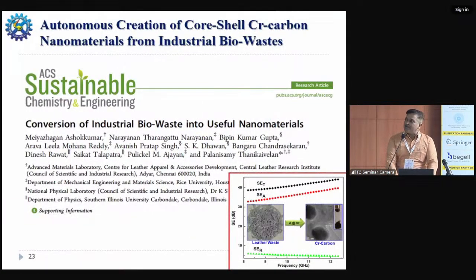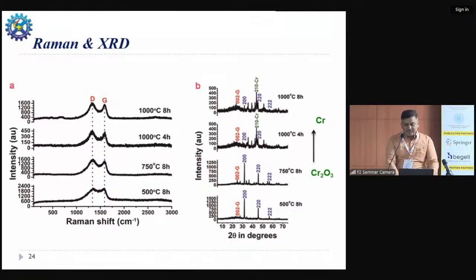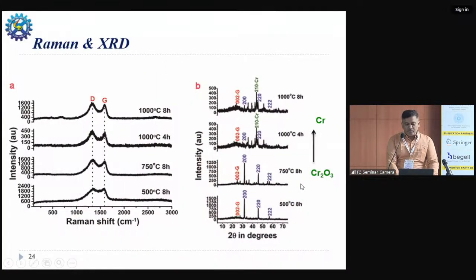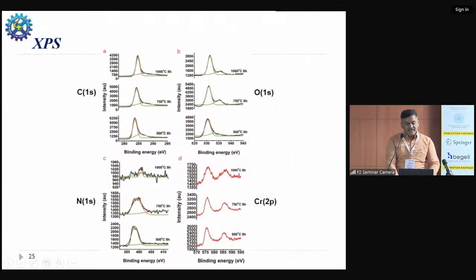And this is another example where we used chromium-containing carbon waste and subjected it to a similar kind of approach. Here we found that at high temperatures, the chromium is converted into chromium oxide at 500 to 750. But the moment you go to 1000 degrees Celsius, the chromium oxide is further converted into chromium. That is what we observed in the XRD. And the XPS analysis shows that the chromium is present in the 3+ form. Hexavalent chromium is toxic, but we are making sure that there is no oxygen, therefore it is not oxidized, and this is proven through the XPS.